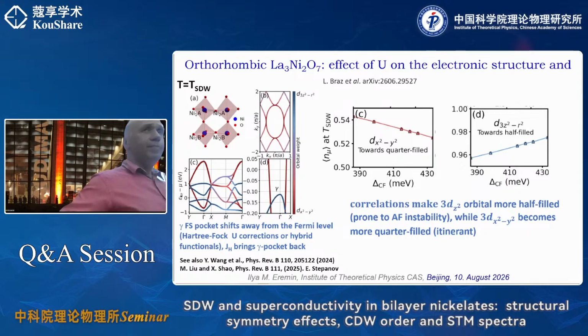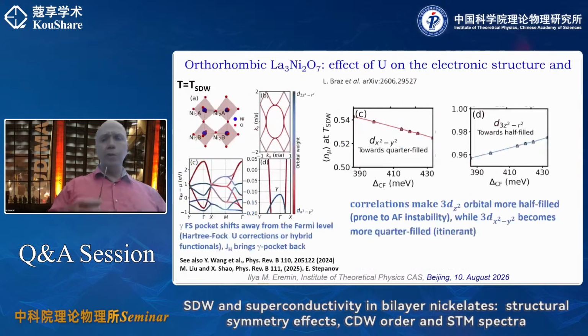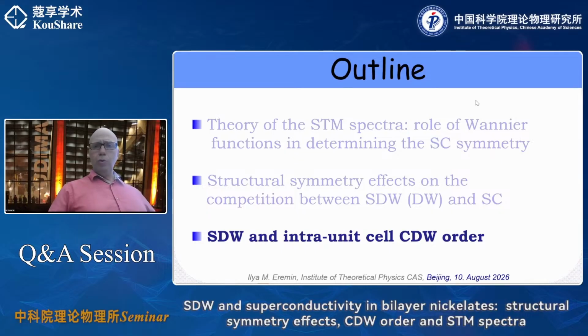Yeah, actually, this point is kind of tricky, if you consider this kind of strong interlayer exchange coupling, right? They form this kind of interlayer singlet. Increasing this exchange coupling is detrimental to in-plane order in principle. To interlayer, right? Because I told you this, right? So this is a strong coupling calculation, you see? So that is what is shown on this slide, right?